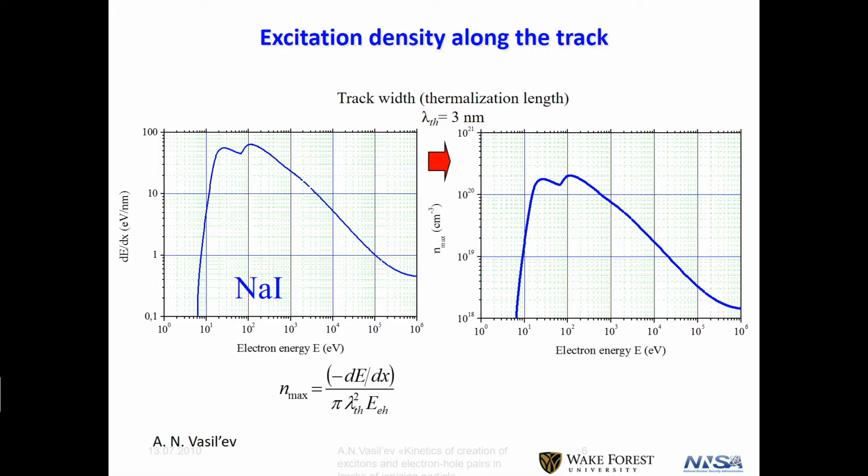And so when we put in, say, the megavolt gamma ray, megavolt electron, you're down here in the rate of depositing energy, or if you like, convert that with the radius, 3 nanometers, into a density. And then when you get up here toward the track end, or specifically here, you've gone up by 2 decades in the excitation density. And that's okay, except the things everybody suspected of causing those nonlinearities had things like dipole-dipole quenching, which is 2nd order, and Auger recombination, which is 3rd order. So you've got something 3rd order in a quantity that's changing 2 orders of magnitude, so you're going to expect the Auger recombination to possibly be changing 6 orders of magnitude in its rate. It's just scary numbers like that to look at.